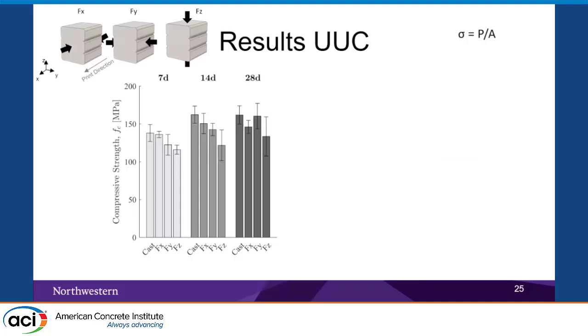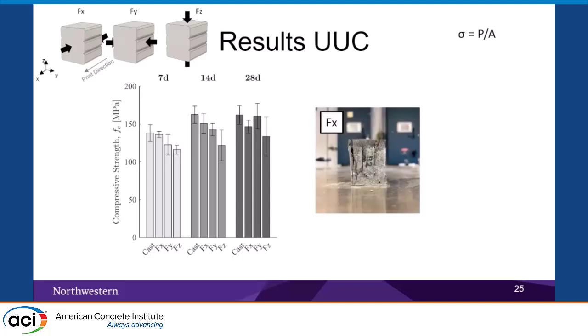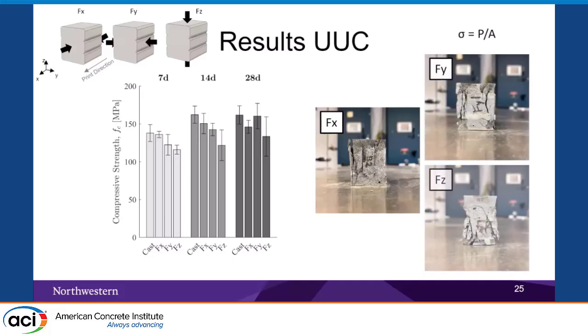Once we add fiber, we still have the anisotropic behavior of the material, but the difference is we have splitting, because we have a weak zone between the printed layers. And when we compare with the samples without fiber, we can see it's a cone failure here.